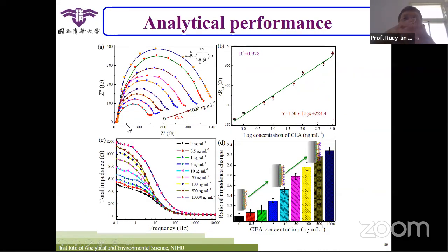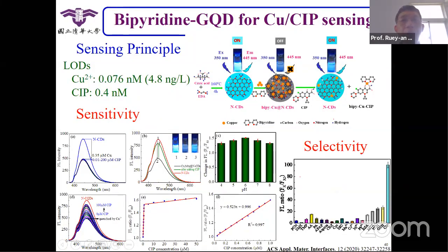The biomarker actually is not a good conductive material, but GQD, gold and PANI are all good electroactive materials. So when their conductivity is high, the impedance diameter will be small. When you add the CEA, it's not a good conductive material, so the impedance increases dramatically. From the diameter of this impedance, we can get a good calibration curve here, and then we can get the amount of the CEA.